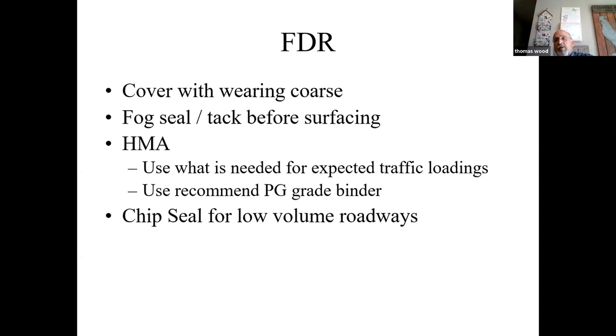I would tell you, if you're doing stabilized full depth or just regular full depth, you need to look at that as the same as new construction, because you're completely breaking the crack pattern up. Use the proper binder. To go to the expense of stabilizing or grinding up and then use a minus 28, you're probably just fooling yourself. So chip seals have been used on low volume roads; I recommend a double chip seal.